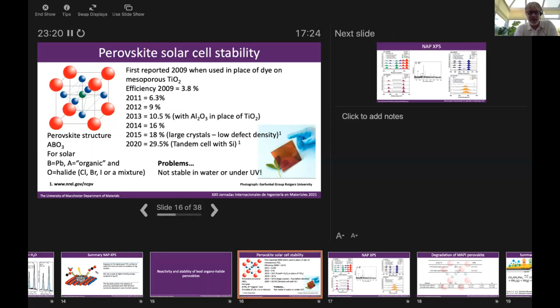Obviously the big problem here, the big elephant in the room with these materials, is they're not stable in water or under UV. And because they have lead, if the perovskite dissolves, then not only do we lose the functionality of the devices, we also potentially have lead leaching out into the environment.